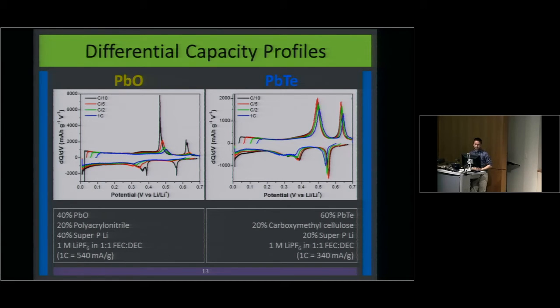If we take one of those cycles for each of the different C rates and compare their differential capacity profiles, each of these pairs of peaks corresponds to one of the lead reactions I showed you before. In an ideal reaction, they would be really close together. The farther apart they get, the more non-ideal it is and the harder it is to make that reaction occur.